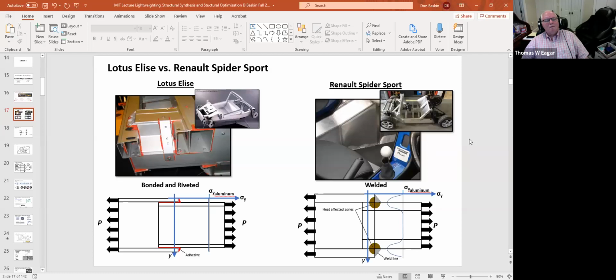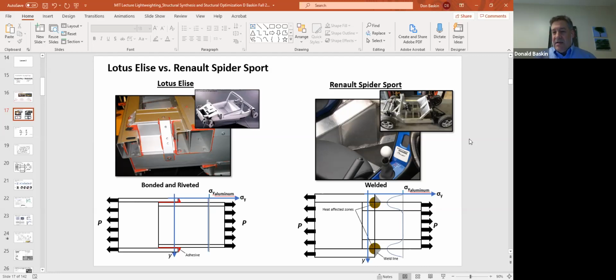Unfortunately, you can't really do that with an extrusion that I'm aware of. So although, theoretically, maybe Renault could have done that on the Spider, they didn't, because I don't think it really was possible. But that would solve the problem, but they didn't do that. So they have a much thicker wall than the Lotus, which is what led to the weight increase.